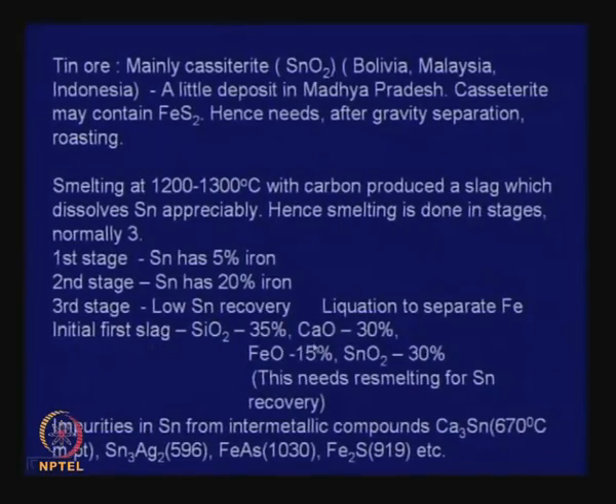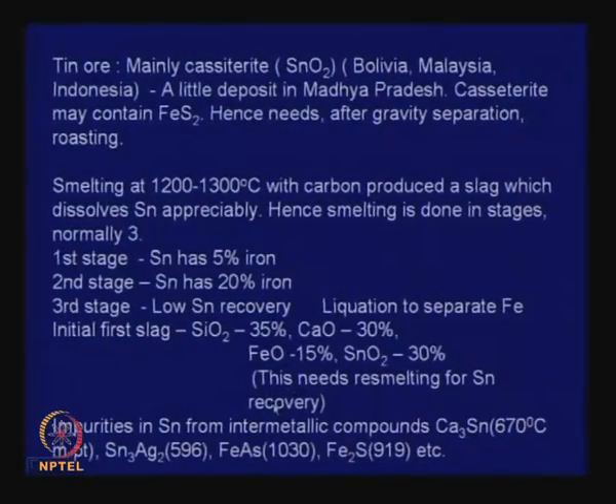Now, the first slag that will come will have silica 35%, calcium oxide 30%, FeO 15% and SnO2 as much as 30%. So, a lot of cassiterite that we want to reduce, we deliberately do not reduce, we let it pass off into the slag in the first stage, because we want to produce the first tin which would not have too much iron. So, that is why the slag needs resmelting for tin recovery.